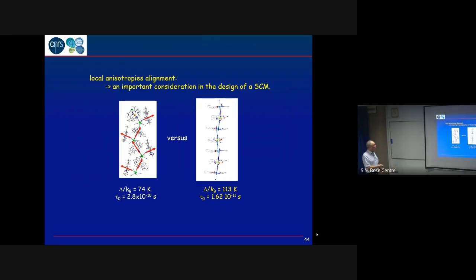So this was just to show you that when we chemists have to design such kind of system, we have to take care about several things to optimize the problem. Of course, you have the spin center that is important. You have the anisotropy that is important. But what is important too is how this anisotropy is organized in space. And this is just a summary of what I showed you before. So here we did not take care about that, and here we took care about it. And we have almost a factor 2 in the energy barrier of the system.